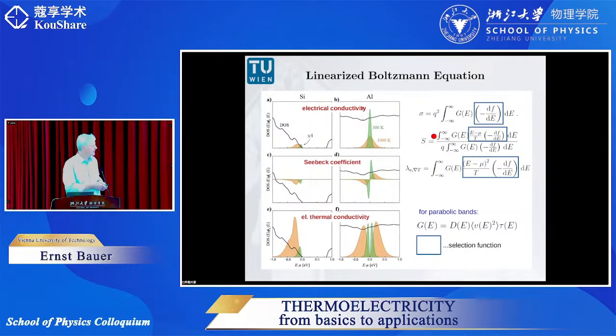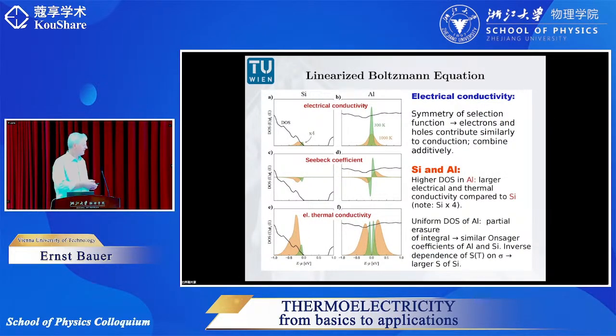You can see when expressing the Seebeck coefficient with respect to all parameters, then there is this part and there is a second part in the numerator and in the denominator. And in the denominator, this part equals the electrical conductivity. So we can already see here that when the electrical conductivity is large, altogether the Seebeck coefficient will be small. And this can be expressed by simple assumptions as it is indicated here. So from our experience, we know silicon has a large value of the Seebeck effect and a small conductivity, and aluminium has the opposite features.